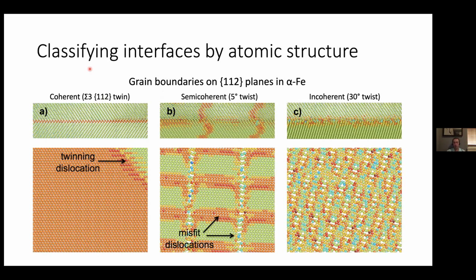And what I want to show you is a simple scheme for classifying interfaces according to their atomic structure. Now, I have to give you a caveat, right up front, that this is not the only way to classify the structure of grain boundaries or interfaces. There are other approaches. However, I wanted to introduce you to this approach because it's, in my opinion, fairly robust, and also because I wanted to talk about this middle class of interfaces here that I'll introduce to you in just a moment. So what I'm showing you on the left here is a coherent sigma-3 twin boundary in alpha iron.